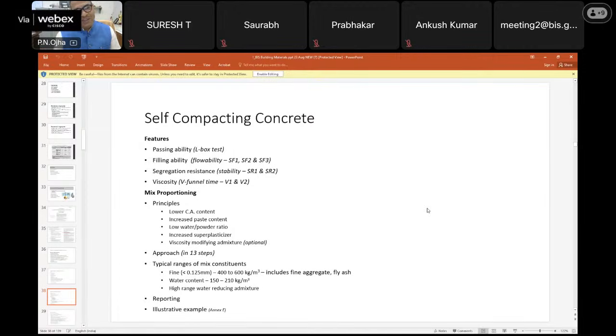But the premise is that the fine content should be in the range of 400 to 600 kg per meter cube of concrete. And what is the fine content here, or powder content? The materials finer than 0.125 mm. Okay, and water content should be 150 to 210 for self-compacting concrete to be designed. And it is essential to use high range water reducing admixture when you are designing self-compacting concrete. But only when one designs it will one understand a little bit of the tricks and art of designing self-compacting concrete.